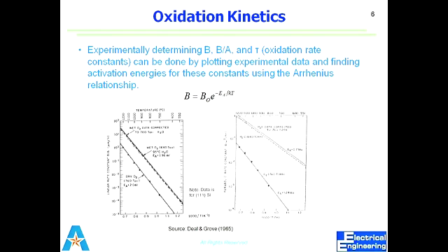But when you know EA, the activation energy would be given in the table, and B naught would be given to you. If you want to find out what my B or the reaction rate is at a specific temperature, you put that T value and you find out B. But usually we always get that from the table. But if you want to find out the value from the given data, then this is the equation that you need to use: B naught e raised to minus EA over KT. You just put the value of the temperature. The rest of the parameters would be given to you.